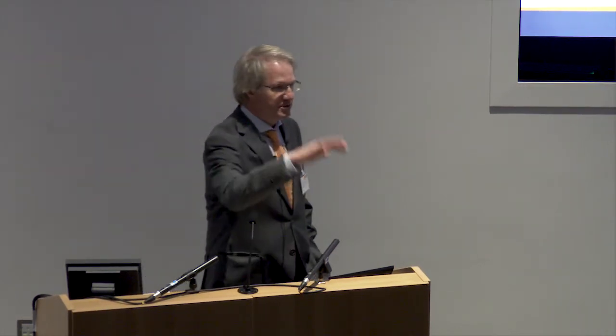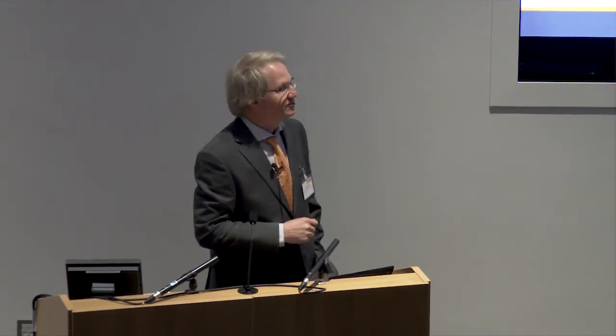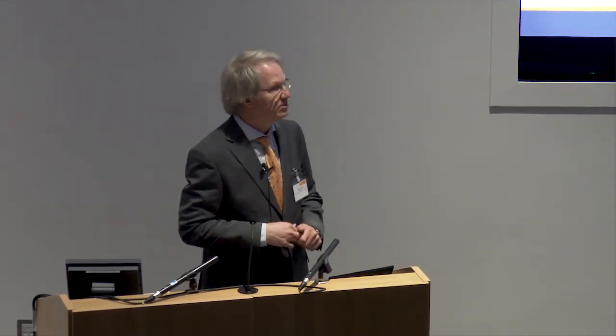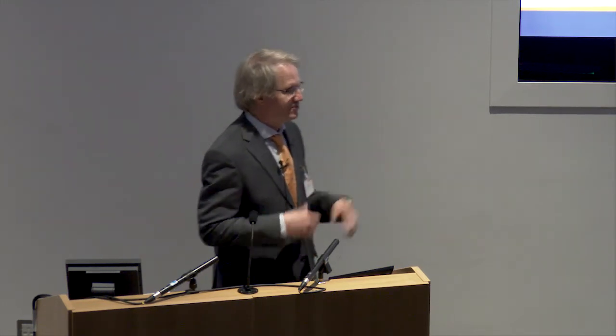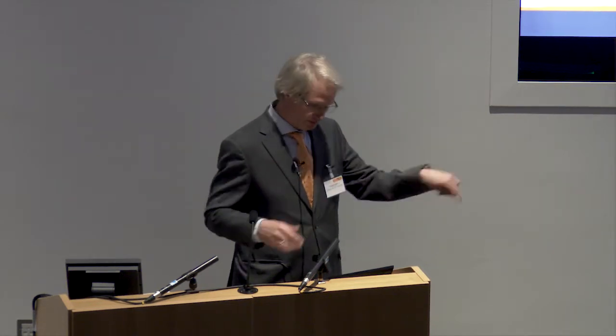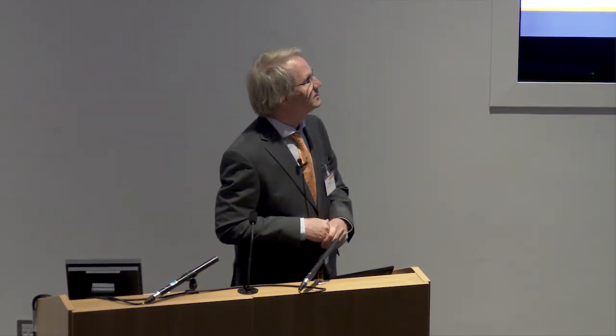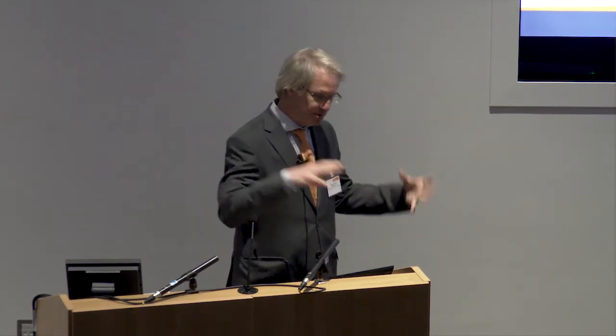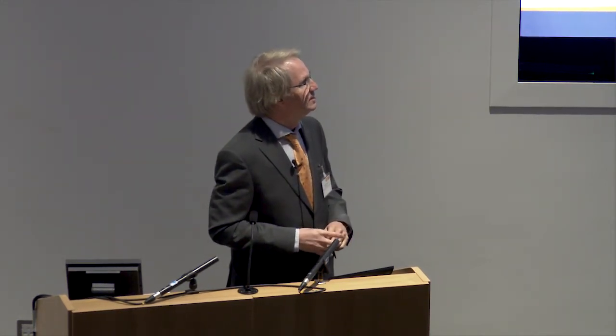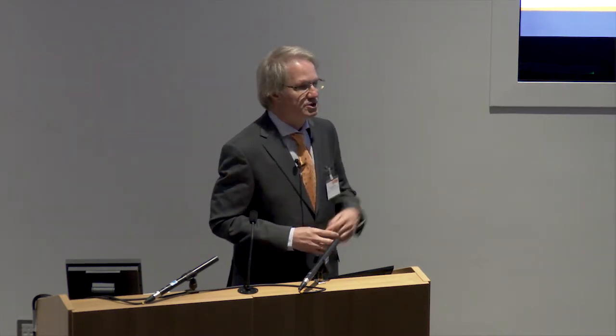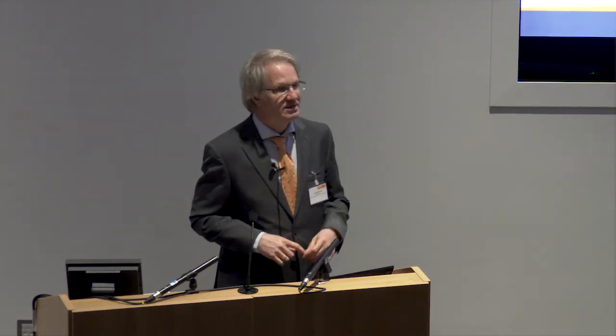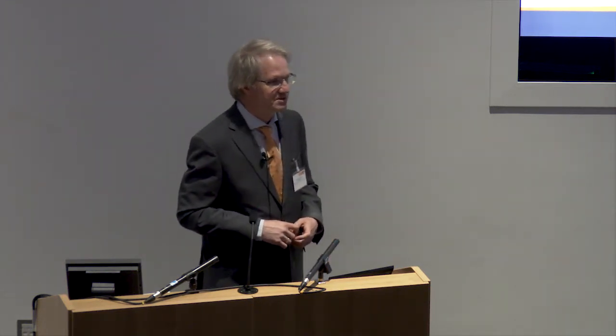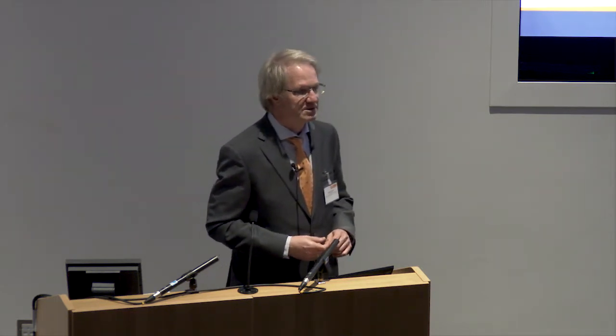To make this process happen, this correlation between the laser power and the angle of incidence has been integrated in a so-called technology module. The technology module takes, for example, an initial NC program defining the path of the laser head, and then this specific laser polishing technology is added on top of this information. And at the end, you will get a laser polishing program which can be used on a normal machine. In case of the ILT, they have equipped a normal 5-axis milling machine with a laser head, and they can run the process over there.